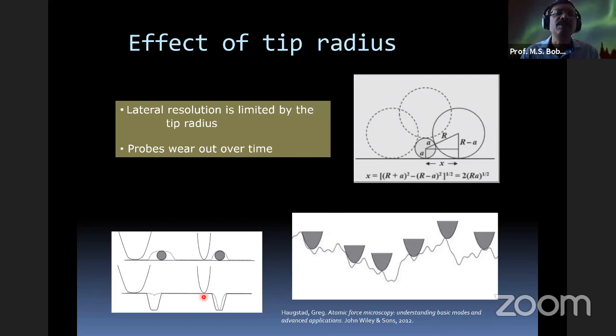For that, we need a very sharp probe. But a very sharp probe will do two things. One, it will damage the surface. Two, it will become blunt as soon as you bring it in contact, because a very sharp tip means stresses are going to be very, very high, which means the tips will break. So typically, the stylus used in the contact profilometer is made of diamond, and the diamond is also given a tip radius.